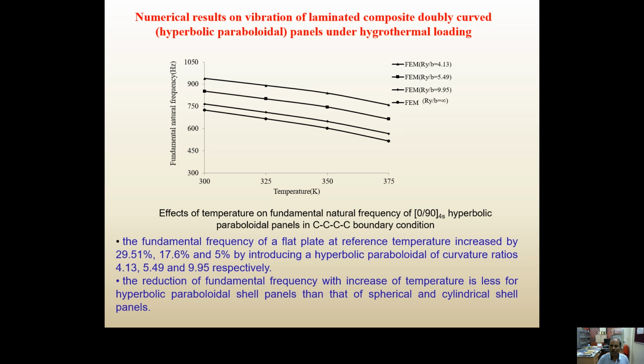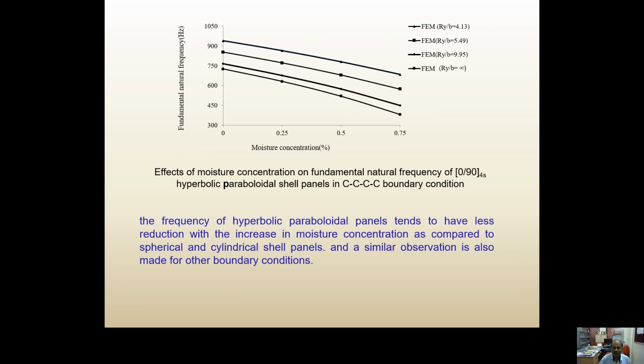Next, doubly curved hyperbolic paraboloid panels under hygrothermal loading. The frequencies look more or less similar to the plate frequency, though it is a shell, and the frequencies decrease with increase of temperature. This is the effect of moisture on the natural frequency of hyperbolic paraboloid shell panels in fully clamped boundary condition. The frequencies decrease with the increase of moisture concentration, but tend to have less reduction as compared to spherical and cylindrical shell panels.